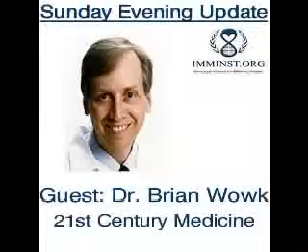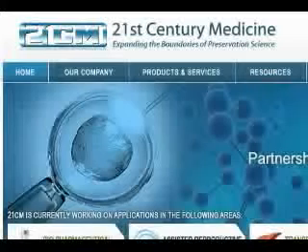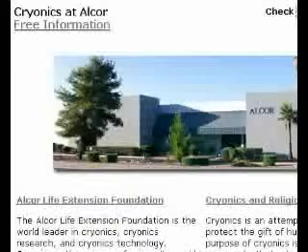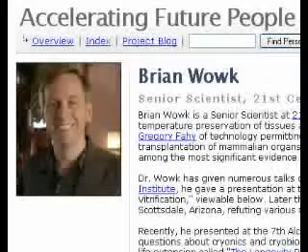Yeah, this suggestion was just made a few days ago by Mike Darwin on the European cryonics mailing list, and you couldn't perfuse a pure ionic liquid into an animal because there would be severe osmotic dehydrating effects from that. So the question then becomes, can you use ions as minor ingredients in a cryoprotectant solution? And from the point of view of using them as minor components, it really doesn't matter whether they're ionic liquid ions or any other kind of ions. It's just a question of, can ions be cryoprotectants? And the answer, as I indicated on that mailing list, is that ions can be used as minor components, but generally aren't used as major components in cryobiology because they don't penetrate cells very well. So they're sort of confined to the extracellular space, and that limits their utility.